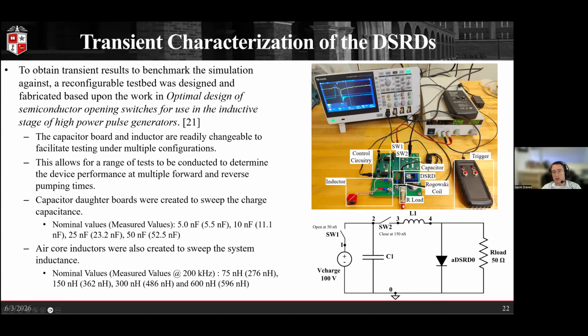And so one of the things that is very particular about both DSRD and SOS devices is their operation is heavily dictated by the circuit they are in. And so one of the things we have after the fabrication of the device to control that is the C1 and L1 values. With that, we wanted to make this test bed where we're able to take these capacitor boards out and the inductors out, swap them in and out in order to sweep across various different conditions. And so with that, we have some nominal values for our capacitors. We intended them to be 5 nanofarads, 10 nanofarads, 25, and 50 nanofarads for our sweep. And then on our inductors, we intended them to be 75, 150, 300, and 600 nanohenries.